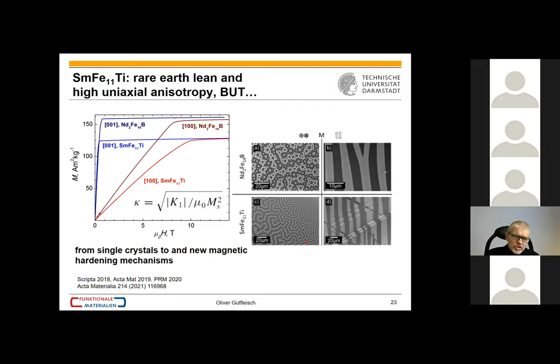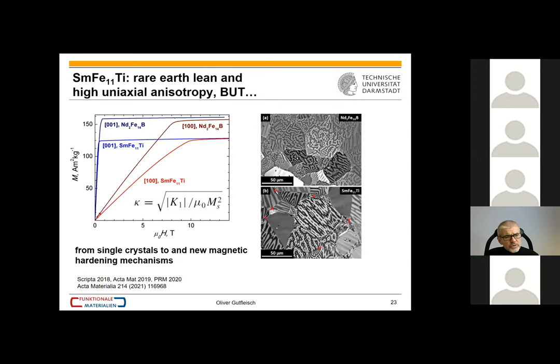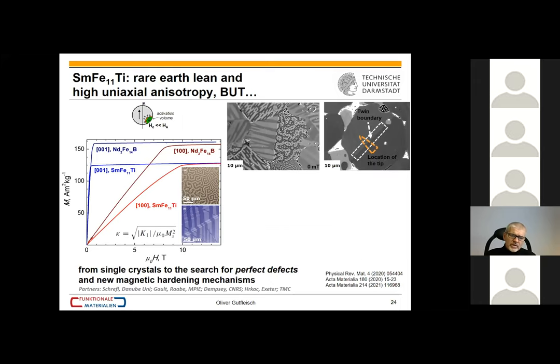So here you see the domain images of the single crystals. And then if you look a bit closely, you can see bottom right that this is no longer a real single crystal, but we see in 112 the formation of a twin structure. And so this is something which we need to learn about. And here we made then polycrystals out of the same material. So that's now the counterpart from single to polycrystal. And then we go further and here you see now that we have the 112 polycrystal. This is a grain boundary here. And you see how the big grain is intersected by a twin boundary here.